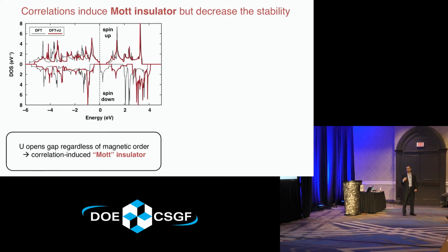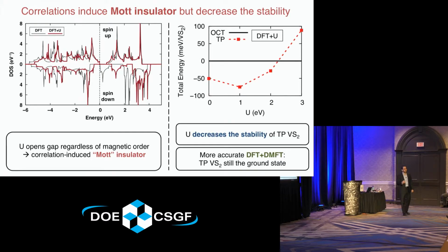So that's very interesting to find. We can also assess how the thermodynamics are affected by the strong electronic correlations. So here I plot the total energy of trigonal prismatic compared to octahedral. So within DFT, it's negative because it was stable. And we note that as we increase U, as we move to the right, initially the stability is actually increased, so it's further stabilized. Though for sufficiently high U within DFT plus U, this trigonal prismatic phase does become destabilized.